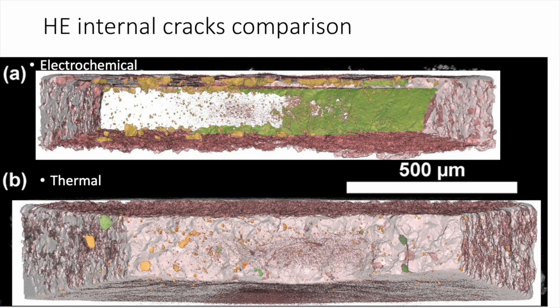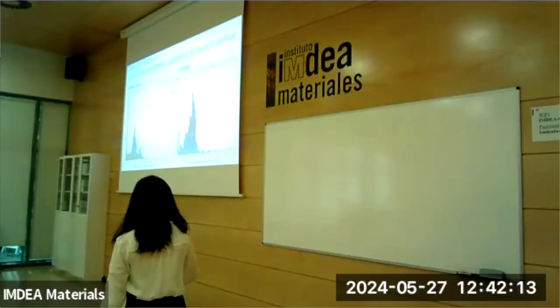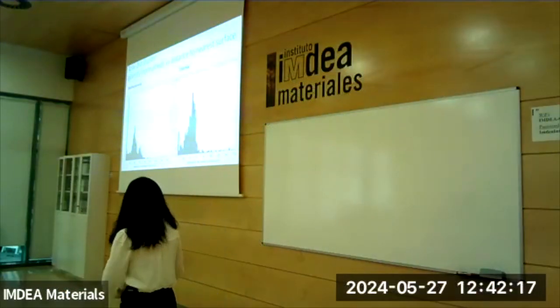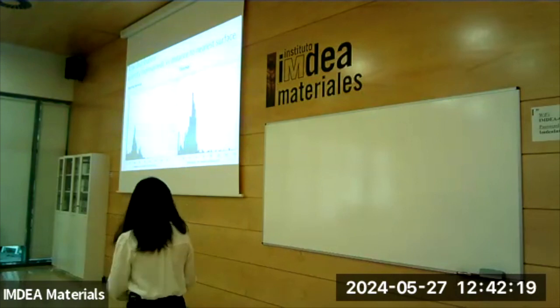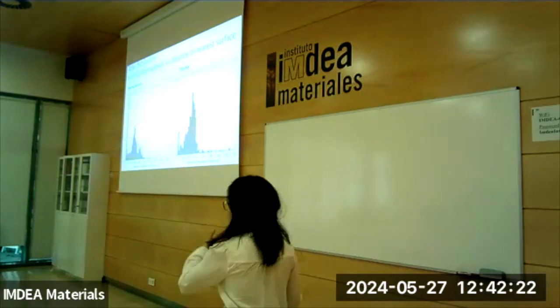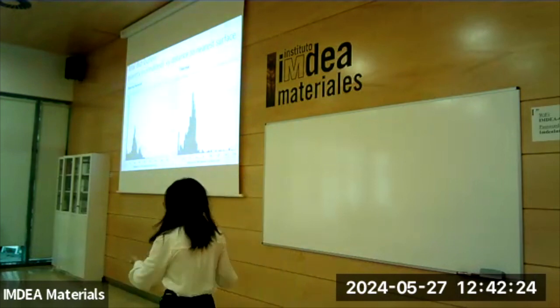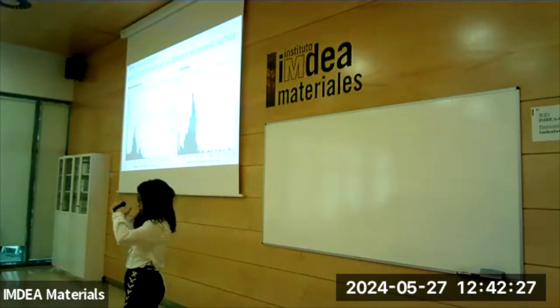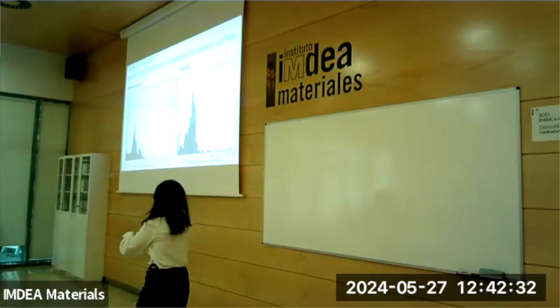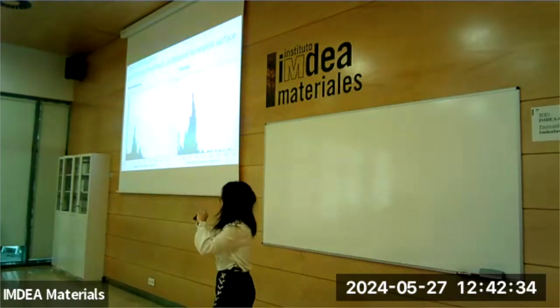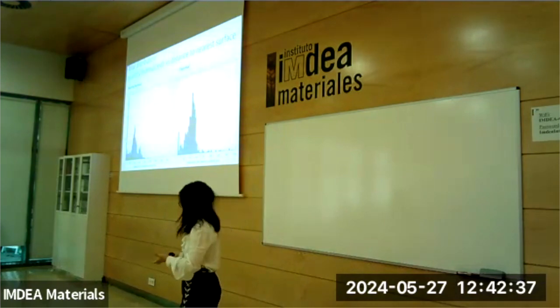This is just a qualitative analysis. So how exactly does the trend differ from the electrochemically charged one to the thermally charged one? So we made this plot. We see the distribution of the quantity of cracks against the distance to the nearest surface. We didn't use the absolute position because when the sample breaks, it has some slight shift, and because of the change in the sample, we cannot use the absolute value. So we measure the distance to the nearest surface.